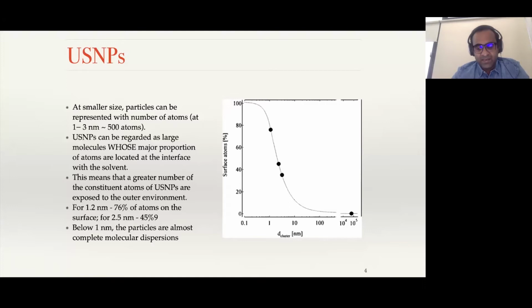But if I start increasing my size, then I'm getting more and more of these atoms shielded at the core of my sphere. Let's say I take a sphere as an example. In other words, those atoms sitting at the core are not really participating in anything, because remember that when we talk about reactivity, and why nanomaterials are very, very interesting, you really focus on the surface atoms. So by reducing the size, we are ensuring that the surface atoms are predominantly present as compared to the bulk atoms.